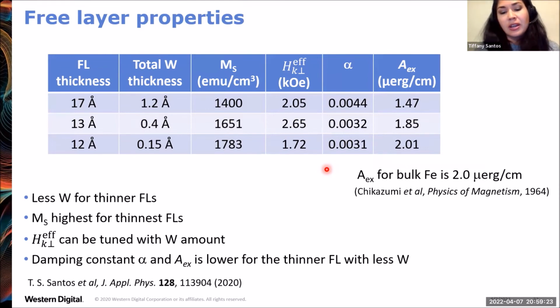So tungsten's heavy. Another popular one to use as a spacer material by other groups is tantalum. These introduce spin orbit coupling, and they're going to raise the damping parameter. It's certainly a general trend that we find that if we do a tungsten ladder beyond what is here, we will see a corresponding increase in the damping parameter for the thicker tungsten layers. So it is basically the thickness of the free layer, and when you reduce it, your alpha also reduces, isn't it? A lot of it has to do with saturation magnetization.